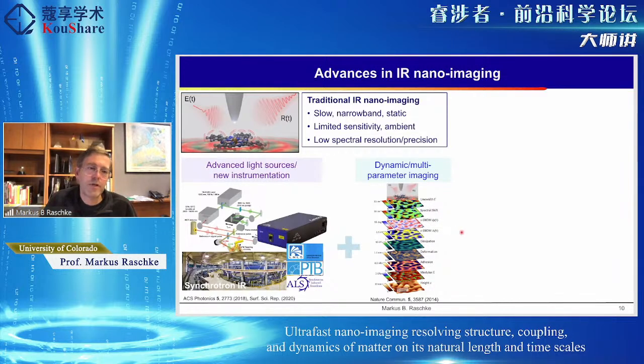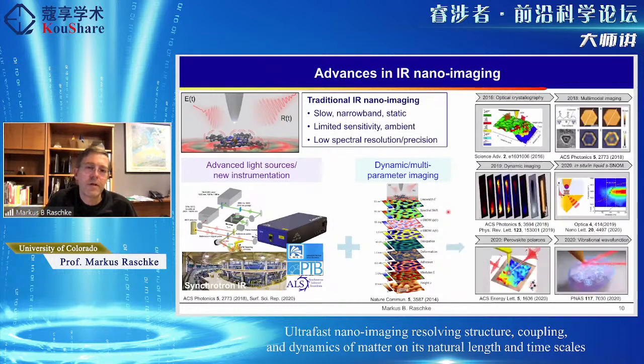And then from the combination of these efforts, as well as implementing compressive sensing and other advanced computational imaging techniques, over the years we've been able to really bring new modalities and new forms of optical signatures. This technique provides new material insight. A couple of examples I will speak about a little bit: the molecular crystallography, the optical crystallography, where we use how the tip breaks the symmetry in the out-of-plane sample direction, which then allows you, through polarization control of the incident infrared light, to determine molecular orientation.